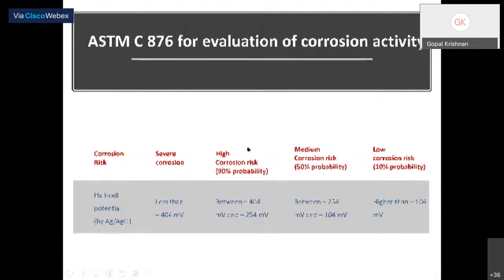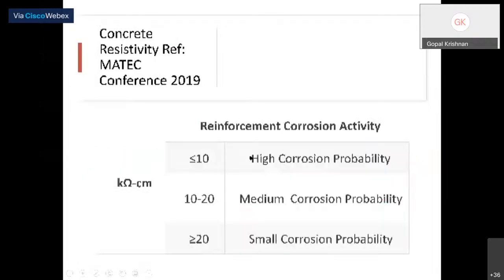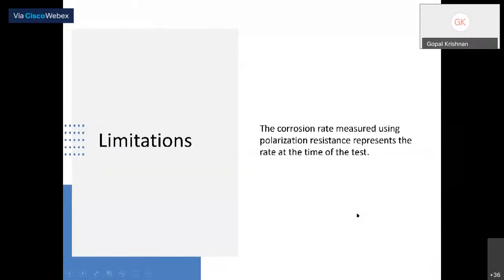How the evaluation of corrosion is given: severe, minus 404 millivolt to minus 254, is 90% probability, high risk of corrosion. Between minus 254 to minus 104 it is a 50% probability, medium. Higher than minus 104 towards the positive, it is a low risk of corrosion, only 10% probability. We can interpret the results accordingly. Understanding the kilo ohms, higher corrosion probability, medium corrosion probability, more than 20 is smaller corrosion probability, from the resistivity point of view.